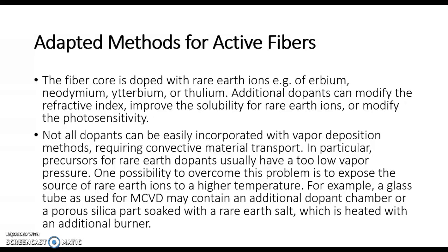Additional dopants can modify the refractive index, improve the solubility for rare earth ions, or modify the photosensitivity. Not all dopants can be easily incorporated with vapor deposition methods requiring convective material transport. In particular, precursors for rare earth dopants usually have a too low vapor pressure.